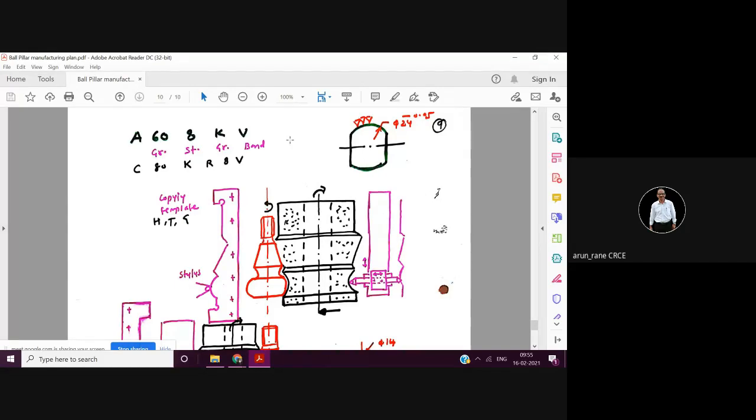In the centers also, the salt or the carbon goes. So the centers which you made, the center drilling you did in the beginning, don't remain true, because they also get oxidized and some scales are also trapped. So those are useless unless you clean the centers. So cleaning of the centers is very important. So you have to remove the scales which are formed in the hardening, and you have to clean the centers properly. Then the second operation is if the components are long and slender, if the L by D